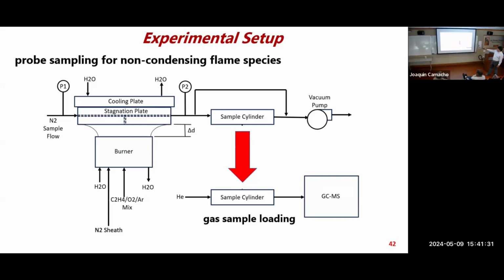Or in my case, I took a sample cylinder, collected a sample, closed it up, and then fed it into the GCMS, the analyzer, in two steps: collect, then carry over to the analyzer, and then inject and analyze. That works relatively simply. But if you were to try this technique with naphthalene or pyrene, or even benzene in my case, these species that condense at room temperature into liquids, you would lose your sample. It will not stay in the gas phase, so you risk either losing a lot of the sample or completely losing it to wall loss. It'll grow a film on your cylinder.